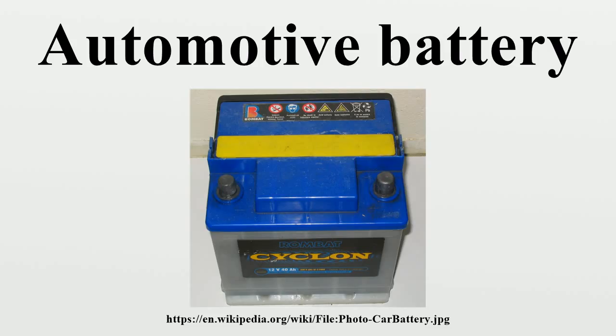Sometimes, the ends of a battery will be severely swollen, and when accompanied by the case being too hot to touch, this usually indicates a malfunction in the charging system of the car. When severely overcharged, a lead-acid battery produces high levels of heat. Warping of the plates is indicated by swollen ends. An unregulated alternator can quickly ruin a battery by excessive voltage. A swollen, hot battery is dangerous.